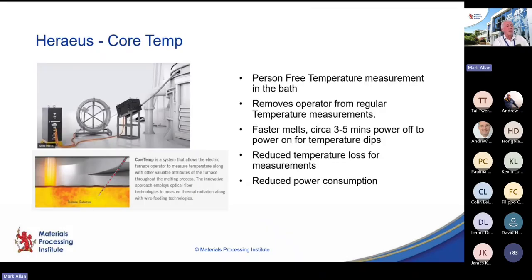Another feature which is important for an R&D furnace is that we want to collect as much data as we possibly can. So continuous temperature measurement via the Heraeus Core Temp system sounds like a good idea from that point of view, but also from the point of view of practical furnace operation, it means we get away from the previous situation where we would have to stop to take temperature dips. And as an R&D based establishment, we would be taking more temperature dips than would be typical in a production environment, and that could have been adding a significant amount of time to our furnace operations. So reduced temperature loss, eliminating wasted time equals improvements in efficiency.